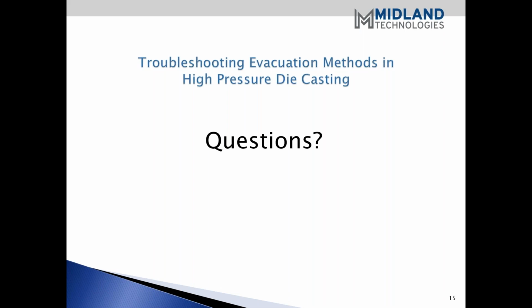But to alleviate that particular problem, if you contact us, we can give you some information on outgassing a casting after you've made it. If it blisters, right away you've got a serious issue. You're going to have a serious issue too if you have minor gases, or even if you've dispersed the gases throughout the casting. I've had some jobs where we were powder coating, and it happens a lot in powder coating because of the higher temperatures used in setting the paint. Wet liquid paint uses a lesser temperature. Plating, of course, you heat the casting up.